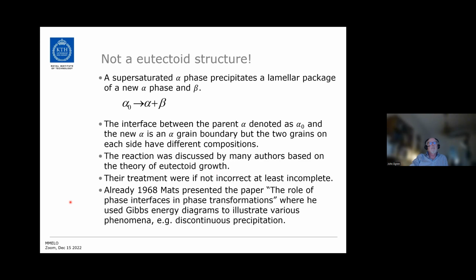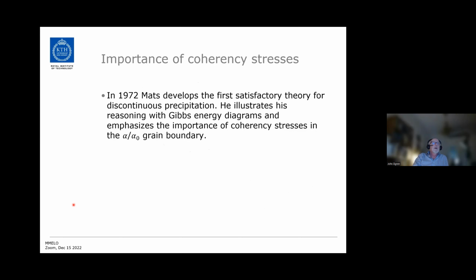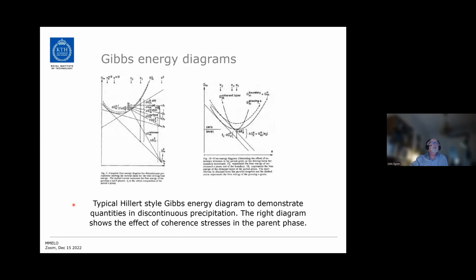Already in a 1968 paper, Mats presented or discussed this process, and he used Gibbs energy diagrams to illustrate various phenomena, for example, discontinuous precipitation. In 1972, Mats develops the first satisfactory theory for discontinuous precipitation. And he illustrates this with the Gibbs energy diagrams, and he emphasizes the importance of coherence stresses in the alpha 0 grain boundary. So here you can see typical Hillert style Gibbs energy diagrams.